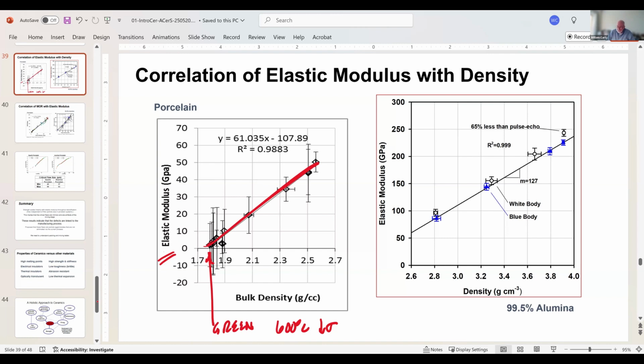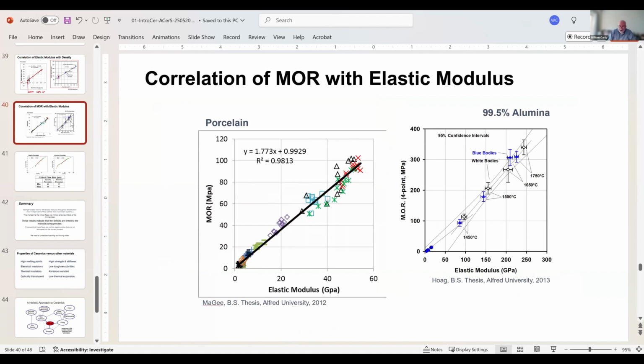And then in aluminum oxide samples done by two of my senior thesis students in 2011, they found the same thing. Here's where you start, roughly, it's actually a little bit lower than that. And then their elastic modulus scales linearly with density. That's good, okay? But when Cecilia then went on and looked at her strength data, here's sigma again as a function of elastic modulus. It also is linear. Now there's scatter in the data. One of the things that was remarkable about Cecilia's work is this is all of the data, not just averages and standard deviations. So you see all the data points and it scales linearly with elastic modulus.